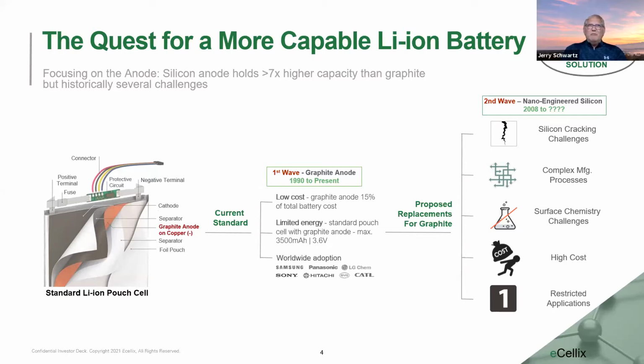There's been research and a lot of investment for the last 13 years since 2008 in evolving to a silicon anode, but most of those have been revolving around a process of using nano engineering because of the notion that silicon expands 3.5 times when fully lithiated, and that causes cracking. And there's a general assumption that under 125 nanometers, you don't get the cracking performance. So a whole host of developers have gone that direction. And of course, a tremendous amount of money has been raised in the process.